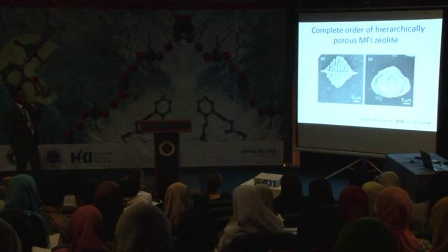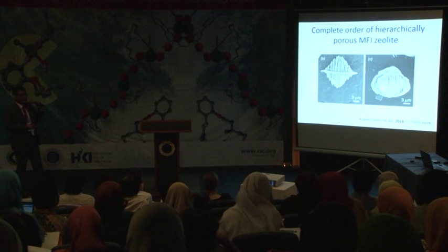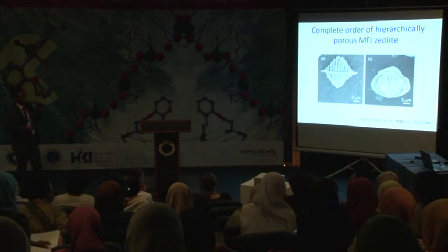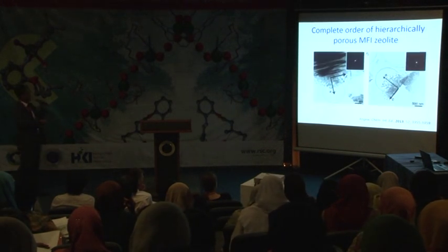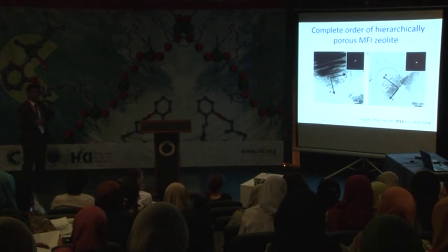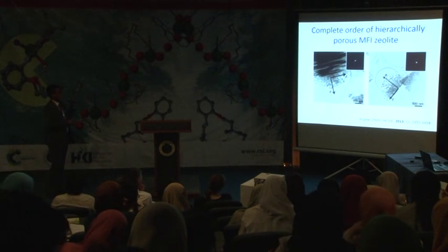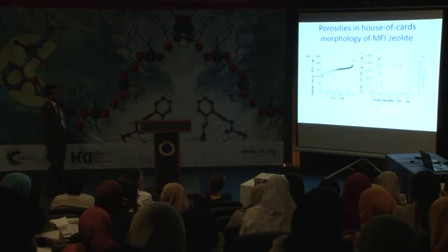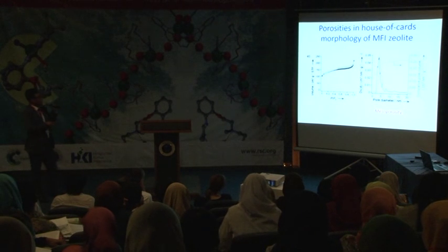I was lucky that this is a photogenic zeolite. So I can make SEM from this side, and I can make SEM also from the top side. So this was lucky, and we published also in quite a good journal. And we look at transmission electron microscope. We could confirm where is the straight channel, where is the sinusoidal channel over there by identifying these axes. And yes, it has porosity within the nanosheet crystals, about 2 nanometers from these pore size distributions.